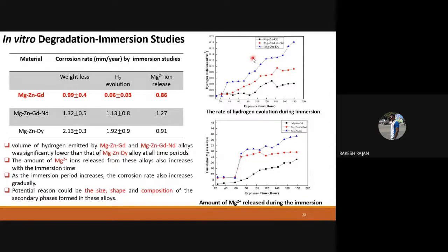This is not a usual technique which you can see in papers, but it is a try for later studies. We established this magnesium ion release at equal intervals of time. Many people have tried hydrogen evolution, but I haven't seen much study of magnesium ion release during degradation, because we put this sample for 180 hours. You can see on the x-axis it represents exposure time, and the y-axis represents the magnesium ion release.